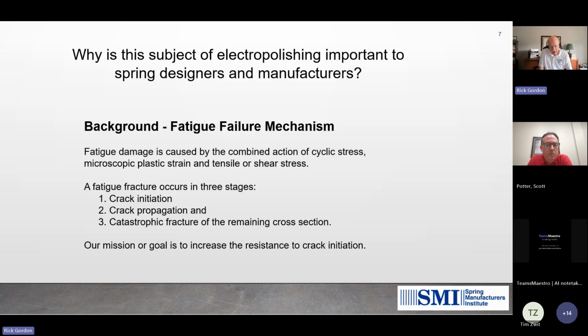Cracks typically initiate at the highest stress location. We learned that the highest stress location on springs is at the surface. And for compression springs, the highest stress location is at the inside diameter of the spring due to the spring helix. So our mission or goal is to increase resistance to crack initiation.